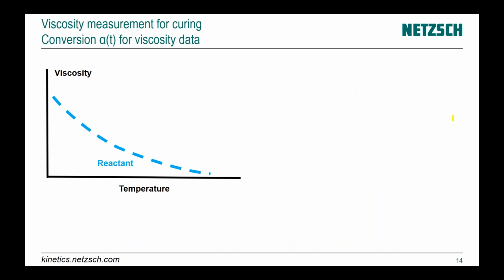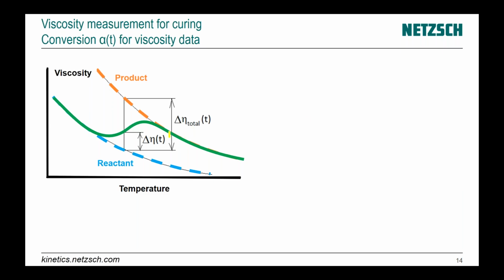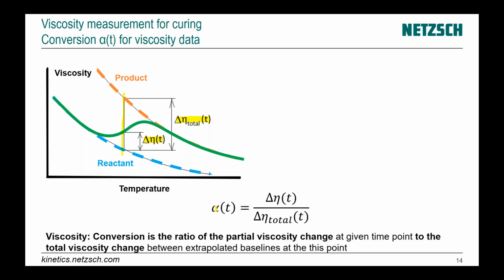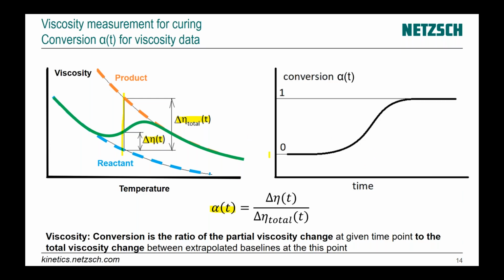Viscosity, we have behavior of reactant, we have behavior of product, and if we have a curing reaction, then there is a step in our measurement. If we make calculation of a change in viscosity, in current viscosity to the total viscosity at this standpoint, then again we have a value of conversion which is changed from 0 to 1. So it doesn't matter what is the original signal.